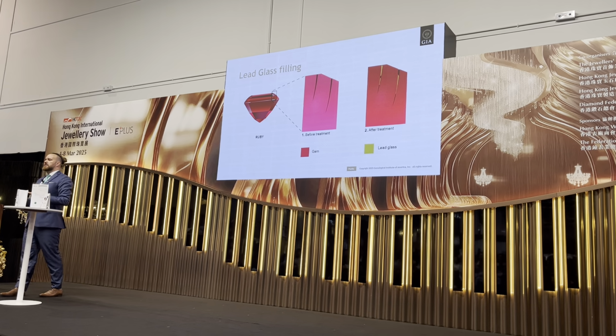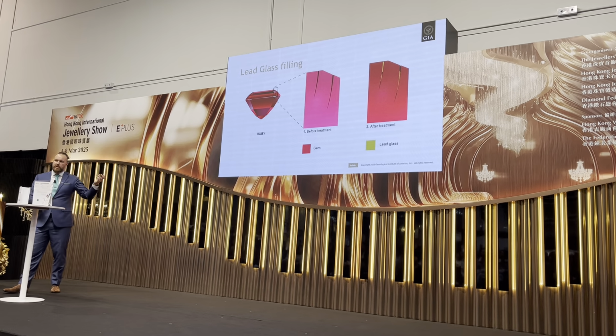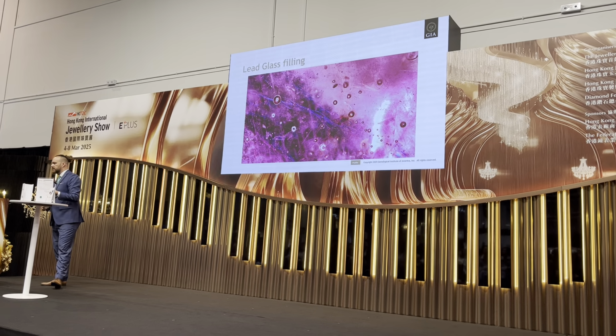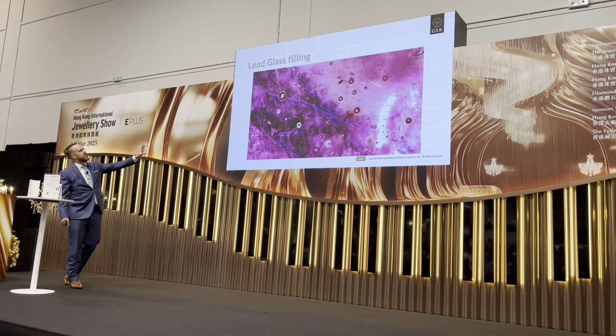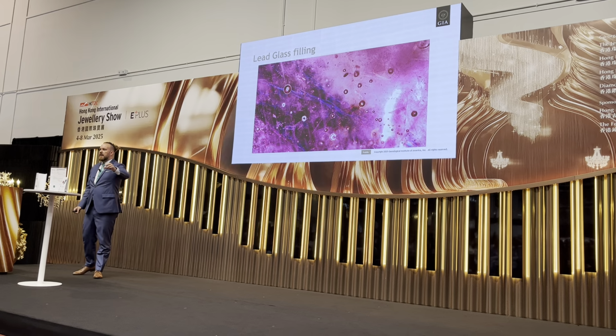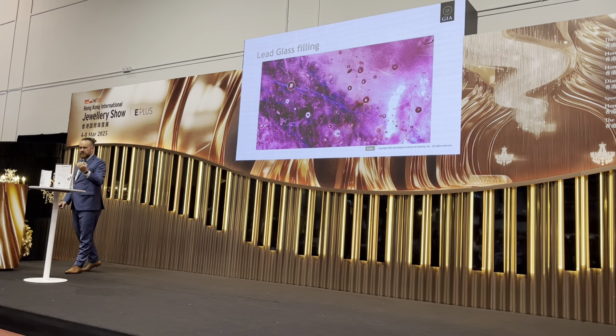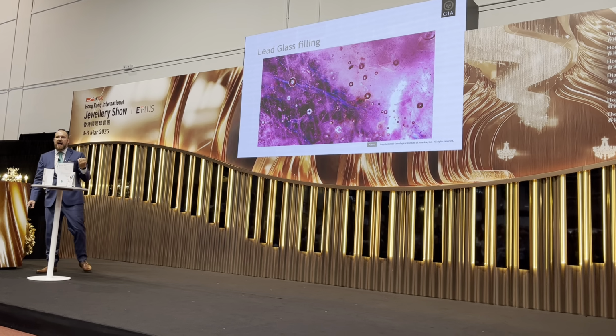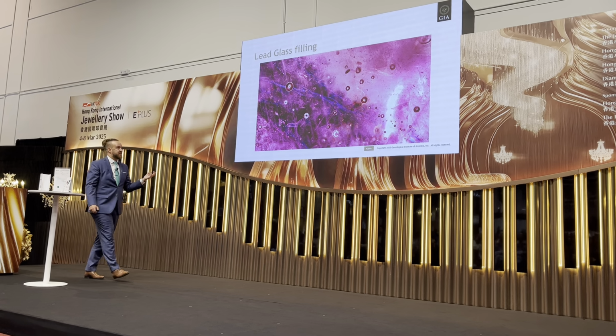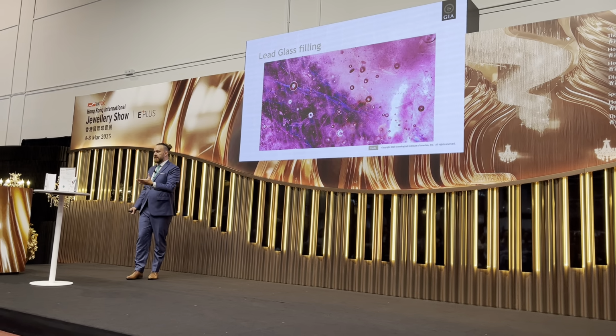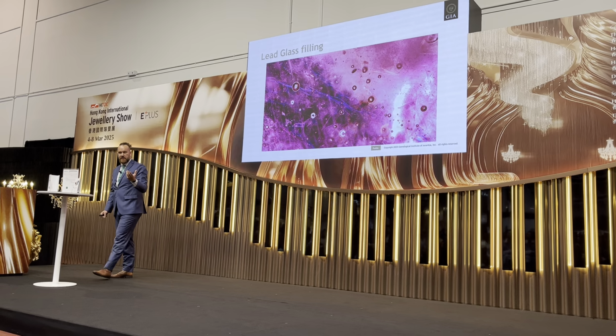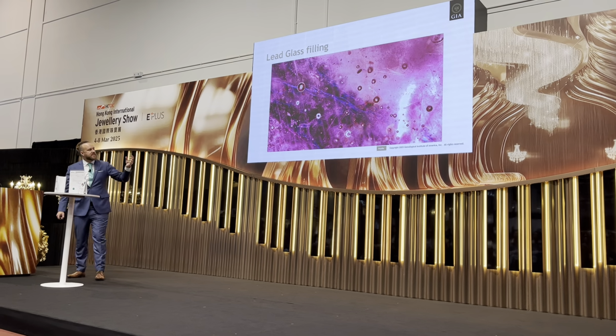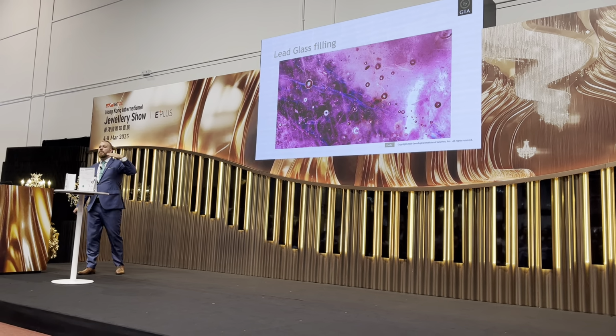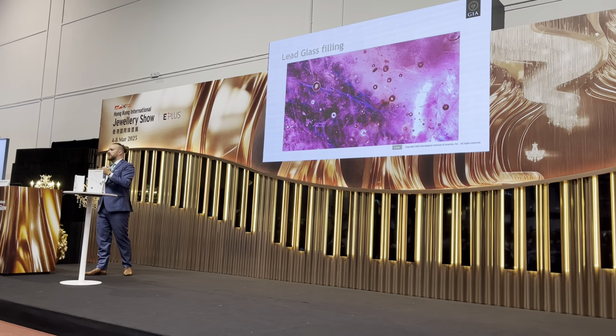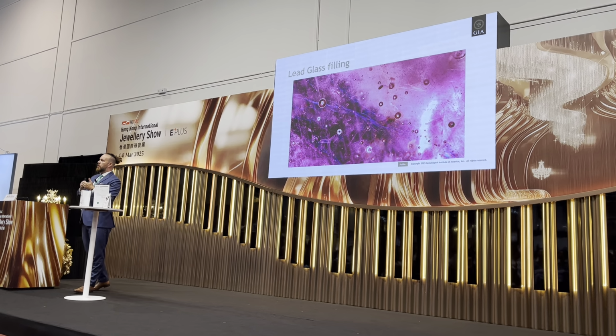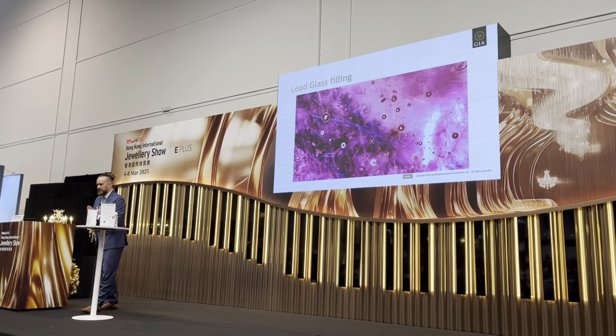Now obviously that has some drawbacks as well, and this is very important to disclose, because a treatment like this, here we can see one of these lead glass filled fractures. That is glass that we put in the fracture. That is not corundum. And that glass has typical glassy features. It has gas bubbles in it, like we see in a lot of glasses. So that's how we can recognize it, where we see all these gas bubbles. On top of that, the refractive index, the optical properties of the glass and the corundum, they're not 100% the same.